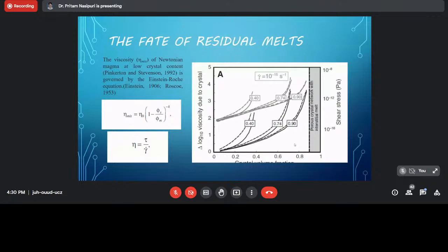After that, I assumed that this is a Newtonian magma. I calculated the viscosity based on the Einstein-Roscoe equation, where eta mix is the viscosity of the crystal magma, and these are the parameters of the liquid. Eta 0 is the liquid viscosity, and 1 minus phi s by phi m. These are the parameters, and minus k is the experimental result. Using this, we can have another equation: viscosity equals stress by strain rate. So if we have strain rate, we can produce what happens here.